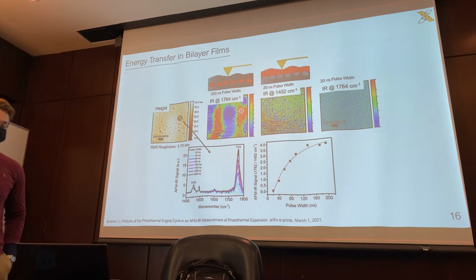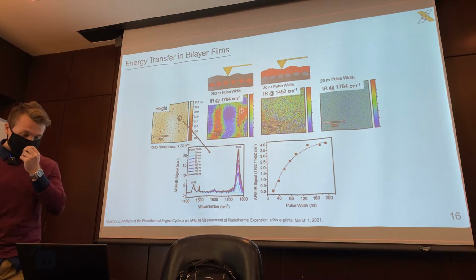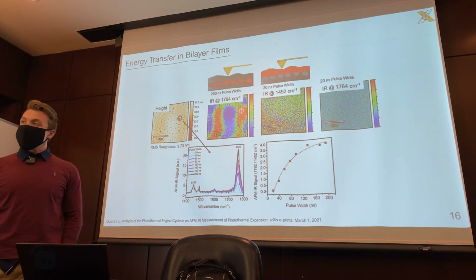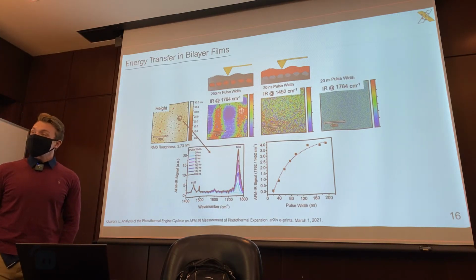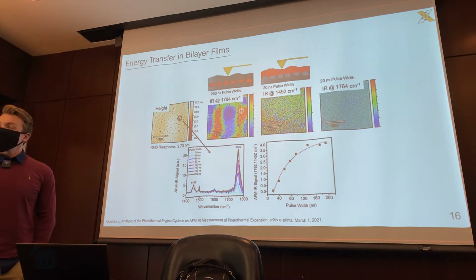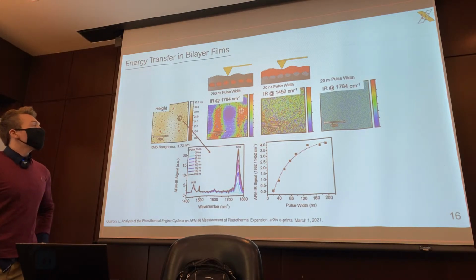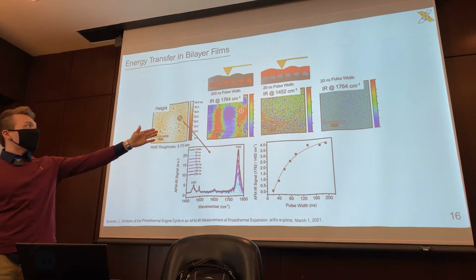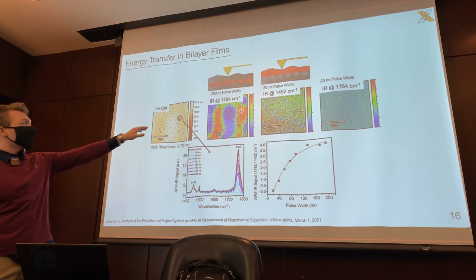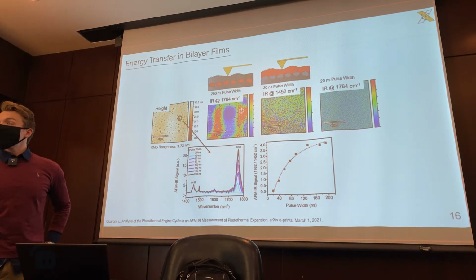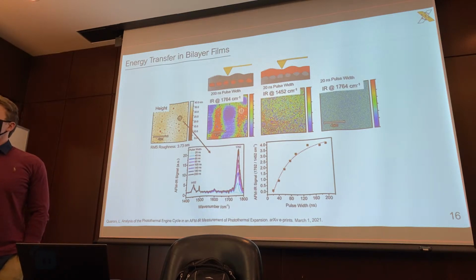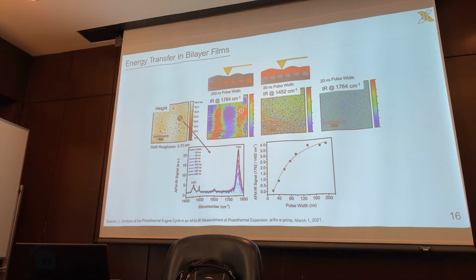Yeah, so for the 1452 you only show one, but if you have a 200 nanosecond pulse width, they still will be the same, right? For the signal. In this case, 1764, this is 200 nanoseconds and this is 20 nanoseconds. I know for the 1764 they have quite a difference when you use the 200 nanosecond and the 20 nanosecond, so that's why you should use the 200 nanosecond. And for 1452, since you don't observe any difference in the nanosecond, then.